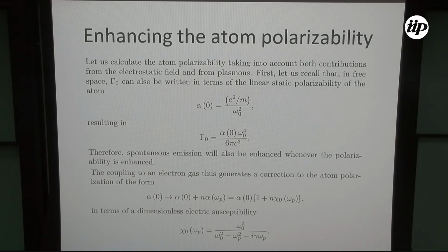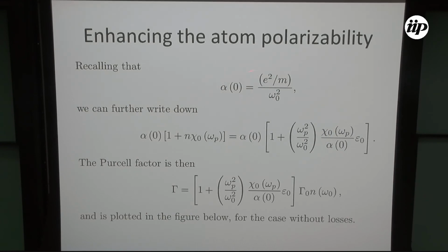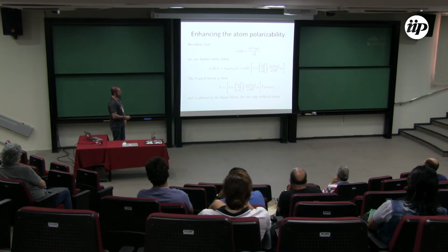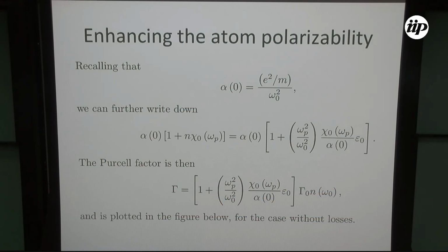It's intuitive to imagine that if these two frequencies are close together, you should have some resonance or amplification effect. This is indeed what happens if we calculate the renormalization of the polarizability due to the presence of an electron gas, which is just the electric susceptibility of the electron gas. In terms of the static bare polarizability, we can rewrite things, and this is the final result. The spontaneous emission rate is the vacuum case multiplied by the index of refraction, but now I also have a correction due to the polarizability. It's a resonance of the oscillating atom with the oscillating electron gas.